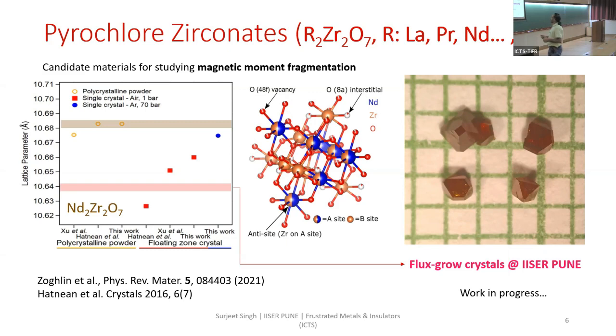And by the way, before I go to our own work, let me tell you that this figure is actually from this Physical Review Materials paper, which is from the group of Steve Wilson. And they have a very powerful furnace. This is a laser heated float zone where they can apply very high pressures. So under high pressures, when you carry out this growth, you can suppress the evaporation of the volatile component. So you can see here is the close to the ideal lattice parameter, the lattice parameter that you would expect when there is no stuffing or anti-stuffing, which means that your stoichiometry is really the one that you want.